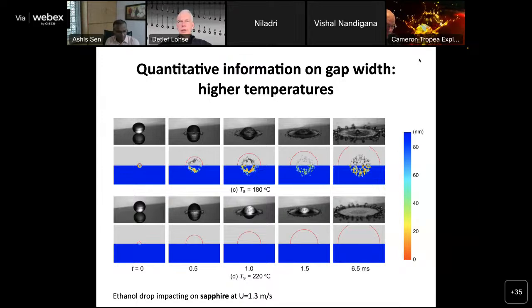It in fact depends on the procedure. When you want the Leidenfrost state and then you reduce the temperature, you can keep the droplet in the Leidenfrost state. We did recent work with Pierre Chantelot in Twente, where we see the transition from the Leidenfrost state towards the touching state, the other way around, as some direct percolation process, and that depends on all kinds of disturbances. So there's not one single Leidenfrost temperature. There is a maximum and a minimum. But this has only come out over the last few years. I think that's super interesting. We call that intermediate state thermal super repellency.